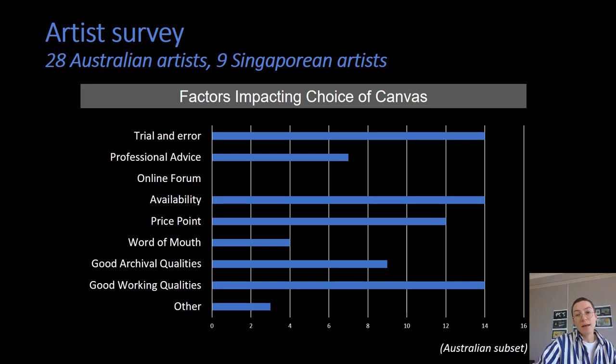Such commercially primed canvases are usually made available as universal with a synthetic emulsion priming suitable for both water and oil-based paint, or with oil priming suitable for oil paint. Commercial developments of priming materials over the past 70 years include transitions from polyvinyl acetate to PVAC acrylic copolymers to acrylics and styrenated acrylics. With ingredients not listed when purchasing pre-primed canvases and minimal information available to artists regarding these materials, the survey findings suggested a need to document commercially primed canvases today.